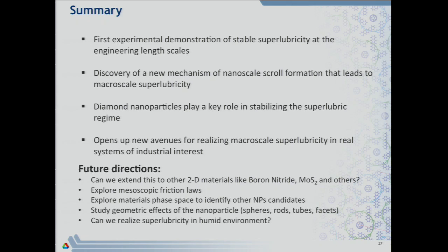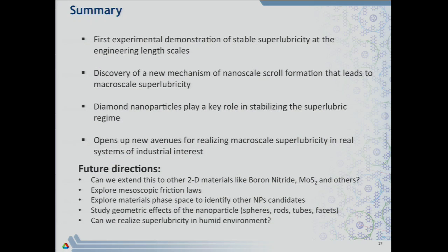This immediately tells us there is an optimal density of graphene and nanodiamond needed to achieve superlubricity. If you add too many, they tend to agglomerate, and agglomeration effects can affect the result. This opens up a whole new area where 2D materials can be used as lubricants. New 2D materials are emerging regularly — silicene, phosphorene, germanene, stanene — and most of them could have interesting lubrication properties that can be screened through simulations.